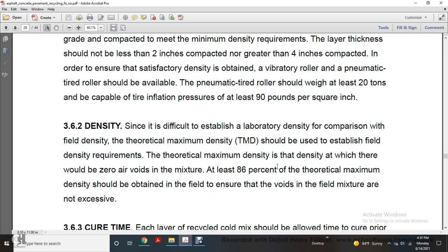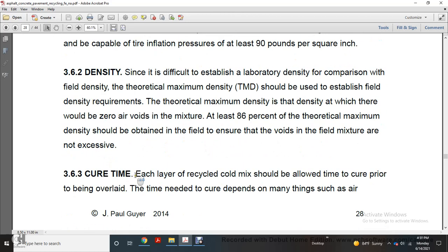Density. Since it is difficult to establish laboratory density for comparison, the final density relative to the theoretical maximum density should be established in the field with the maximum requirement. The theoretical maximum density is the density of the mixture with 0 air voids. At least 86% of the theoretical maximum density should be attained in the field to ensure the voids in the field mixture are not excessive.